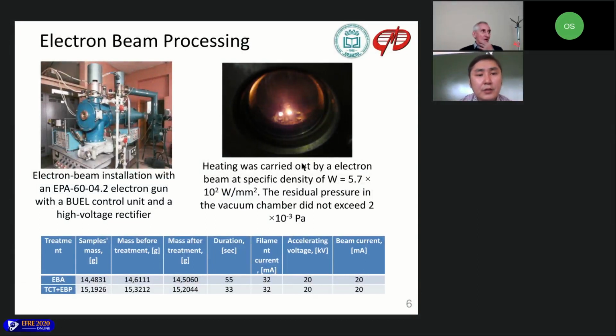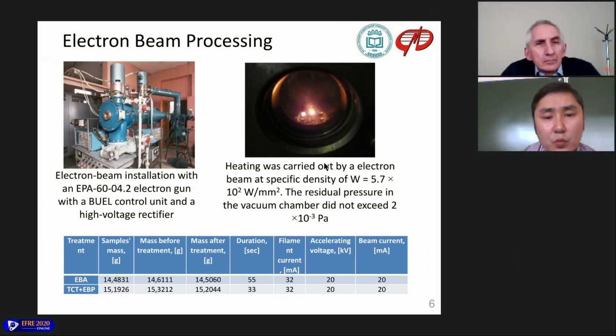So electron beam processing was done on installation, which is presented on the left. Treatment parameters are discussed on the right side, where you can see specific density, residual pressure in vacuum chamber. And let me point your attention to the table below, where you can see the mass change before and after EB.